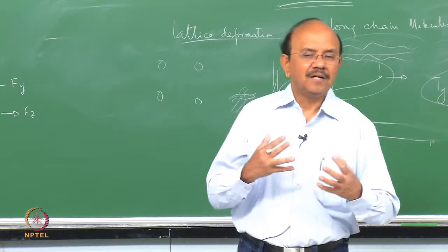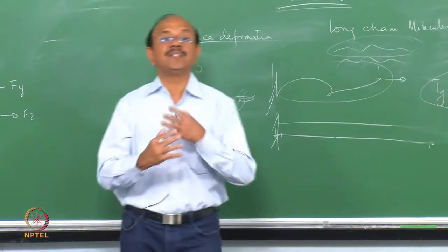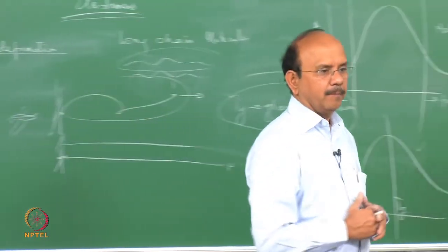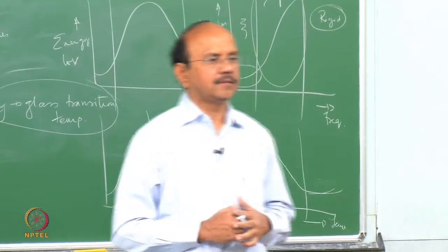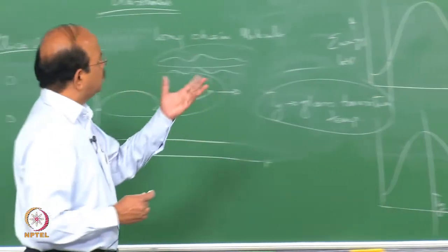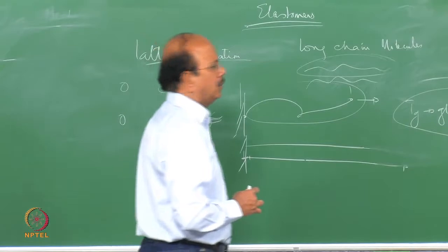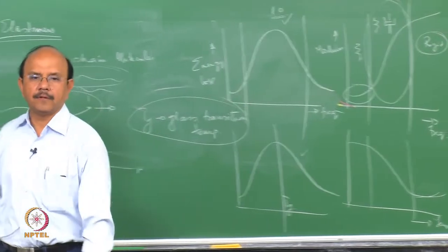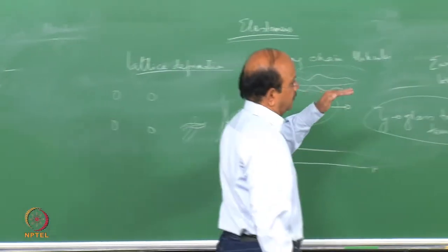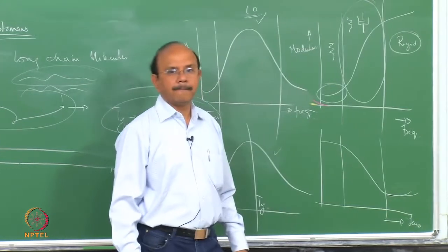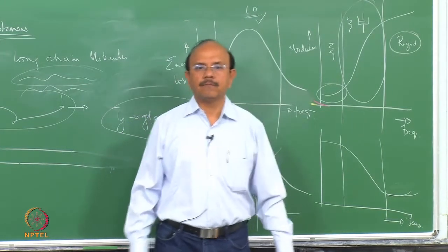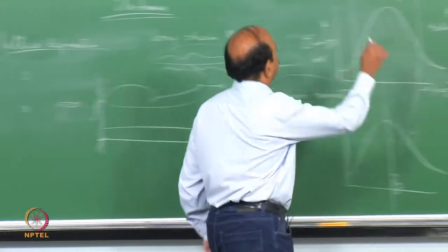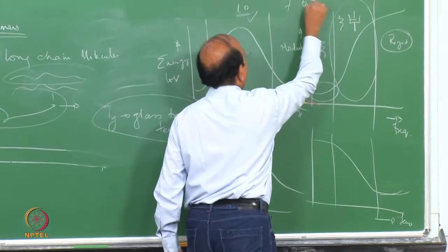So there is an interaction between these two. In other words, there is an equivalence between the frequency and the temperature, and the equivalence is inverse. It is usually said that when the frequency increases by a factor of 10, there would be a change of temperature of 7 to 8 degrees.